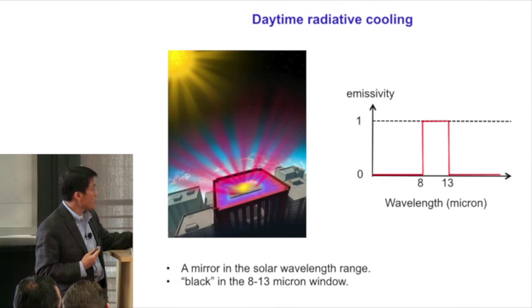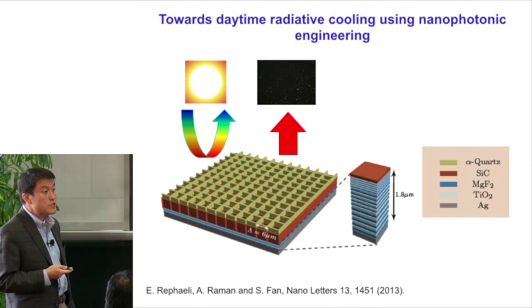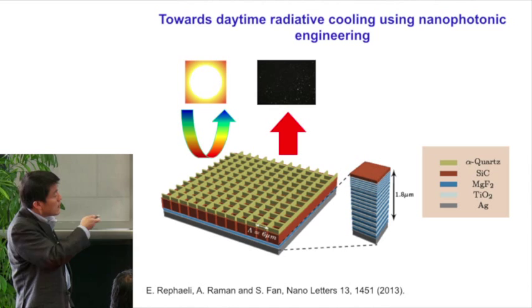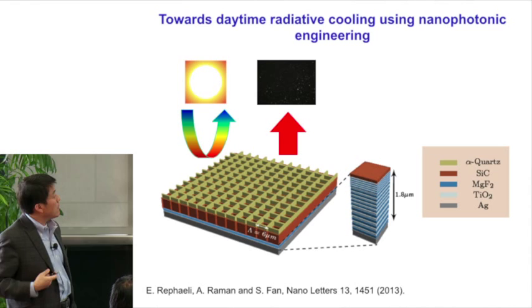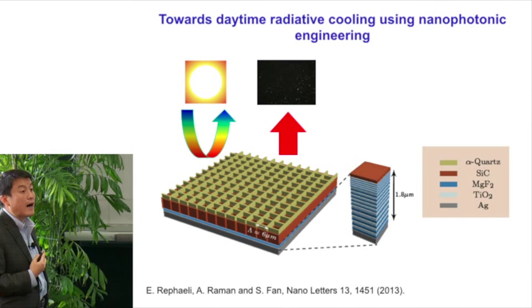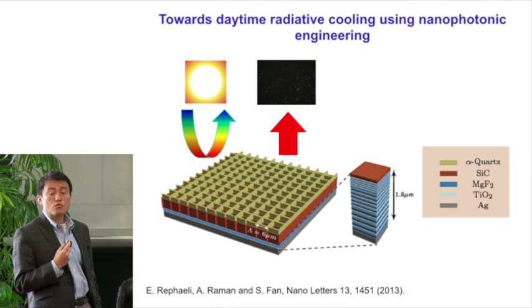So the first thing we did is use numerical simulation to design some of these structures. And here are some of our initial designs. We tried to design a broadband solar mirror with a chirped multilayer film. And then on top of it, we put a photonic crystal made of quartz, silicon dioxide. These are materials that, through their lattice vibration, have a very strong phonon-polariton response, and consequently they emit thermal radiation very strongly.